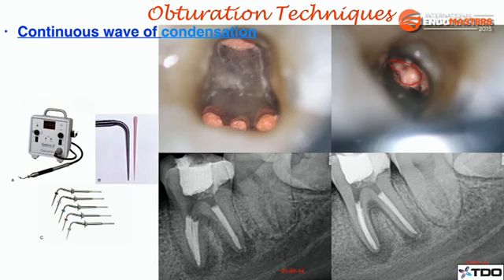The technique employs an electric heat carrier, the System B unit, and pluggers that have 0.5 millimeter tips and tapers of 4, 6, 8, 10, and 12%. The electric heat source permits a variable temperature setting. The recommended temperature setting for the System B unit is 200 Celsius degrees. There is enough evidence already that demonstrates that the rise in temperature produced by this equipment and technique is within safe limits, and that has been the case for a couple of decades. After selecting an appropriate master cone, a plugger is pre-fitted to within 5 to 7 millimeters of the canal working depth. Placing the plugger deeper in the canal may enhance the flow of the gutta-percha.